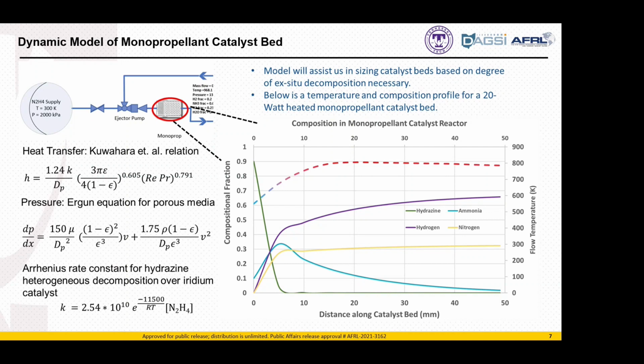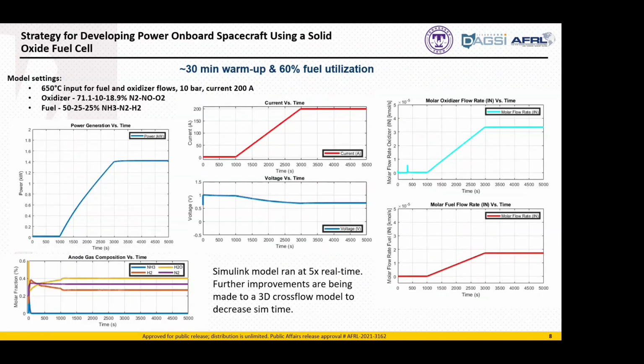And this Simulink design enables us to vary things like porosity and particle size as well, along with the heat input can be controlled transiently. So this was using a 20-watt heated monopropellant catalyst bed. So this just elucidates some of the system level, high-level analysis that we can do here at the beginning of the project to outline what components are going to be necessary in order to get this SOFC to run in space. Here you see a Simulink simulation of a 30-minute warm-up of this fuel cell.